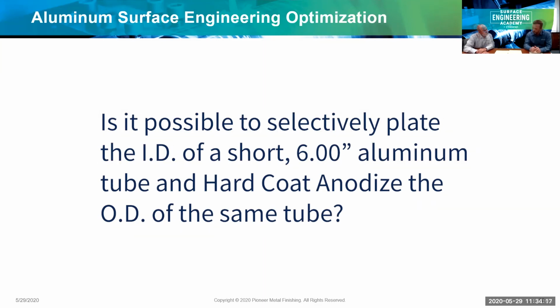Is it possible to selectively plate the ID of a short 6-inch long aluminum tube and hard coat anodize the OD of the same tube? Yeah, that's a combination we've done in the past, and that's where electroless nickel comes in, where you can do the hard anodizing on the OD, and then we could mask the OD off and then do the electroless nickel on the inside, because you don't need electricity to make electrical contact for the nickel plating process. And as long as the solution can flow, that electroless nickel will deposit.